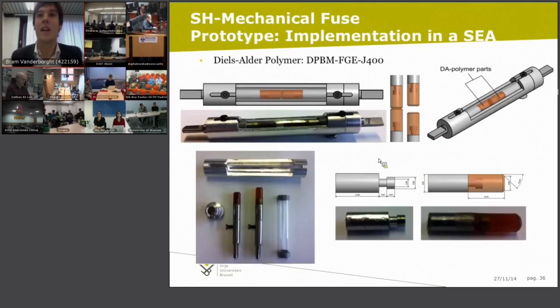Here you see how we did it. Here you see a CAD drawing, and here you see a picture of it. You see two parts of it, and then we make a reduction of the diameter of the polymer parts, so we know that it will always break at this point. In this case, we use a brittle version of the polymer, the J400, so there is no elasticity in it. One of the future ideas is to make the compliant element of a more elastic version of this polymer. But the problem here is that you have necking, so it's more difficult to do the self-healing. That's for the next phase in the project.